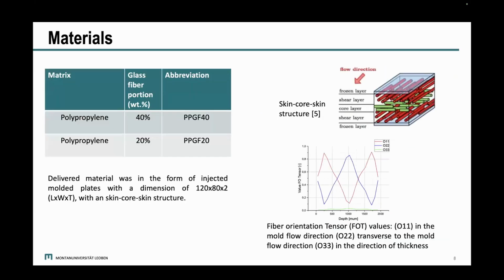Here we have a look at the materials which we use for this study. In this study, we use two different short fiber reinforced polymers, once polypropylene with 40% glass fiber, and once polypropylene with 20% glass fiber. The material which we received from our partners were injection molded plates with dimensions of 120 × 80 × 2 millimeter. And the plates had a skin core skin structure.